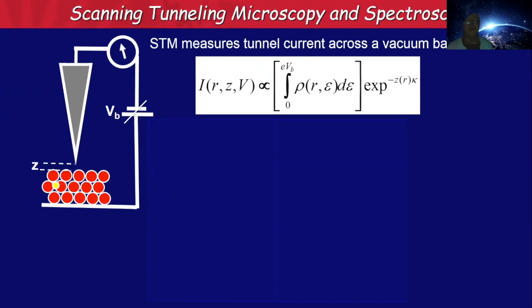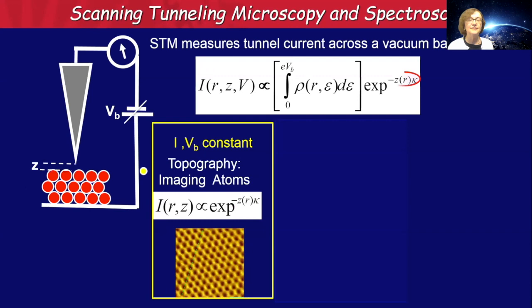In order to see these effects, we can do scanning tunneling microscopy. So bring a sharp metallic tip to your substrate and apply a voltage between the tip and the substrate. Bring it close, but without touching, and monitor the current that flows in this circuit. This is going to be a tunneling current. The tunneling current depends on two parameters: the distance of the tip to the substrate, and the density of states inside the integral here. That allows us to make two measurements.